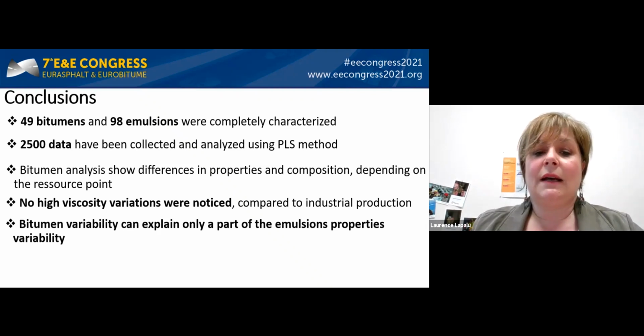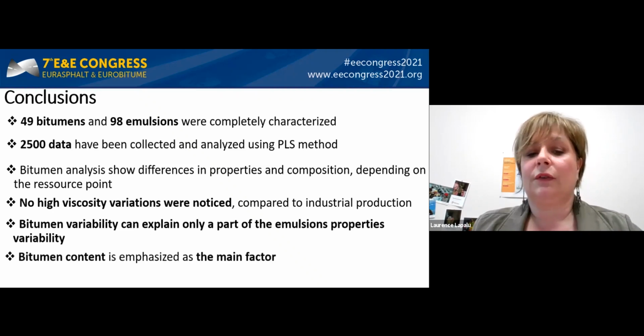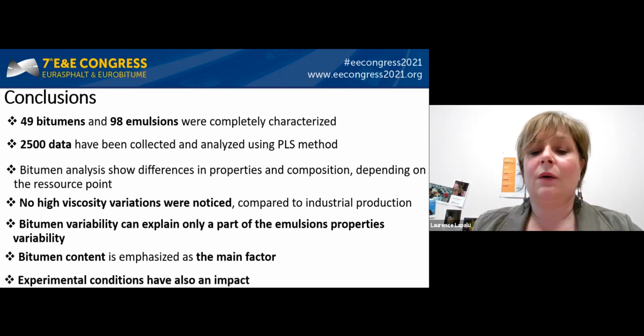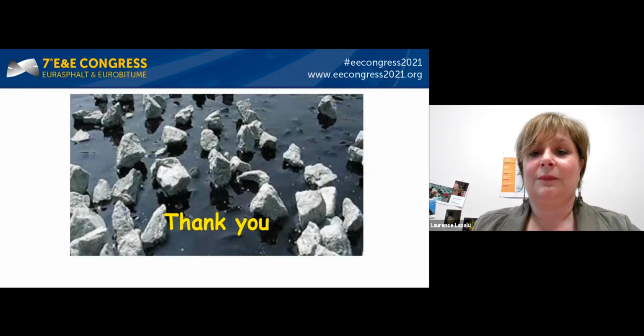The statistical analysis has highlighted that the bitumen variability can explain only a part of the emulsion's properties variability, and the bitumen content has been emphasized as the main factor. But there are also other factors impacting the emulsion properties, and especially the emulsion viscosity, that are the experimental conditions to produce these emulsions. I thank you for your attention.